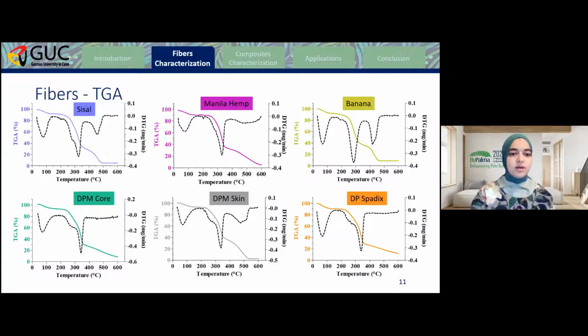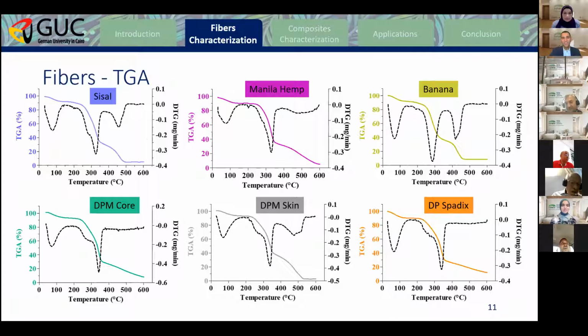For the thermal properties, 6 TGA graphs along with the DTG graphs are present in this slide. The 6 types of fibers had 4 thermal decomposition stages. The first stage corresponds to the dehydration, followed by the decomposition of hemicellulose, then the decomposition of cellulose, and finally the decomposition of the lignin. And it was found that nearly all the fibers were thermally stable up to 250 degrees Celsius.